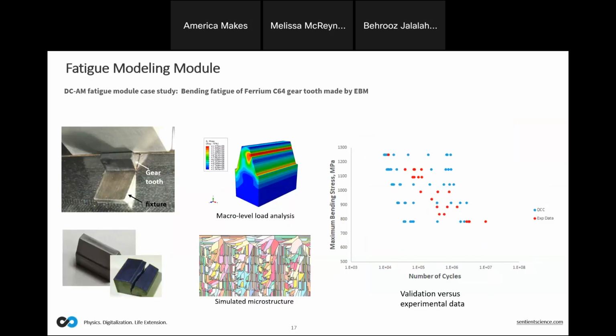For the next one, I have a little bit more complex geometry. It's still not that much; it still is at a coupon level. It is a single gear tooth under bending fatigue. You can see the experimental setting that was used on the left-hand side. Also, you can see one of the broken samples at the bottom, and you can see the crack started and propagated close to the root of that gear tooth.